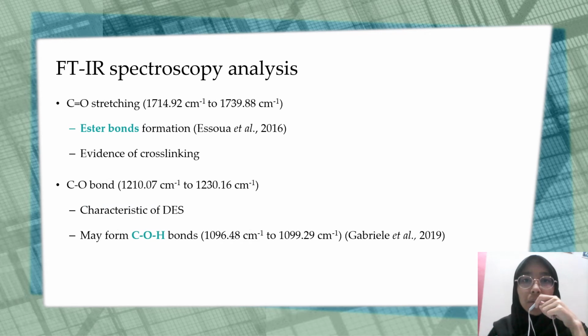Carbonyl bond become more intense because more citric acid increased the carboxyl group to form more ester bond with hydroxyl group of pectin. CO bond is characteristic of DES and may form COH bonds, which were shown by the fourth peak in the spectra earlier.